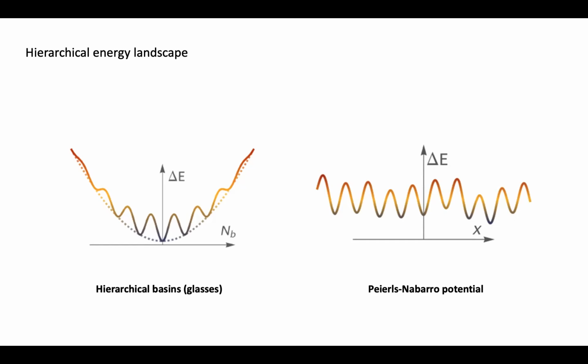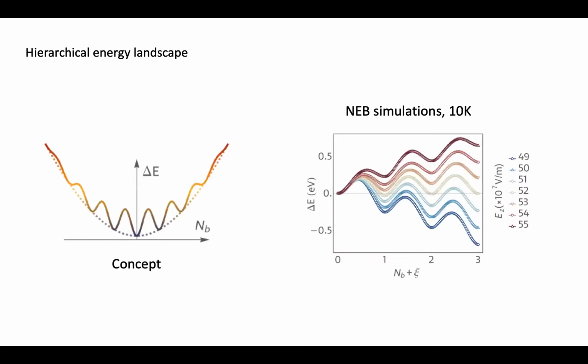And what we wanted to do is to explore this picture, because those hierarchical energy landscapes are also interesting from the point of view of glass physics. This is the seminal idea that glass behavior stems from this kind of energy landscape. So we did some calculations using the nudged elastic band method. And here we show the results under different bias fields for the change of energy with respect to the number of bubbles. And as you can see here, indeed, the picture proves to be what we thought it was.